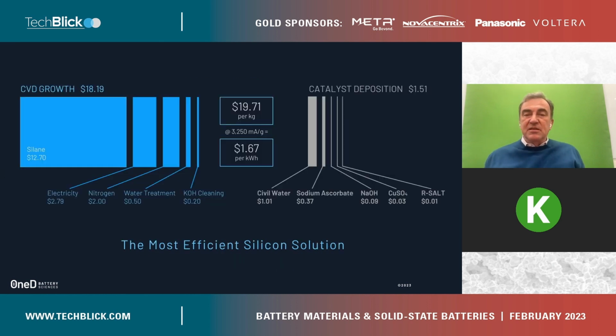Now, a lot of people don't believe in the cost, so we designed this slide to explain exactly where the costs come from. On the right-hand side, you have how much it costs to deposit the catalyst. We use a copper catalyst to decompose silane, and that costs less than $2 per kilogram of nanowires. And the CVD growth, which includes the precursor, the silane, the electricity, the nitrogen, etc., all included, even the yield loss, the two of them together is less than $20 per kilogram of silicon nanowires. And of course, the graphite is the substrate. And at the current reversible capacity that is indicated, that works to a variable cost of less than $2 per kilowatt hour.